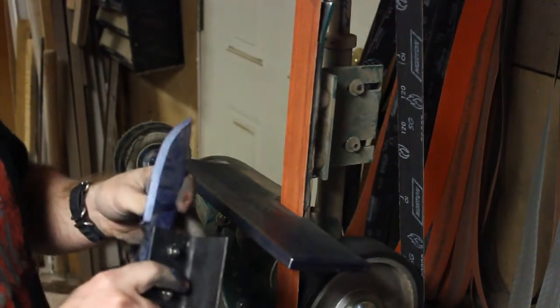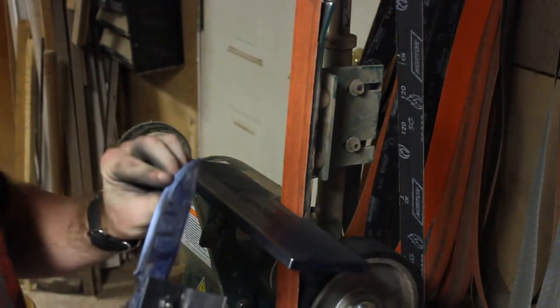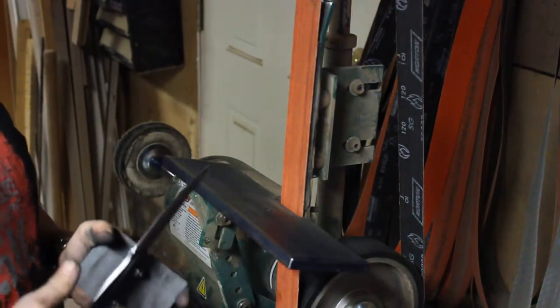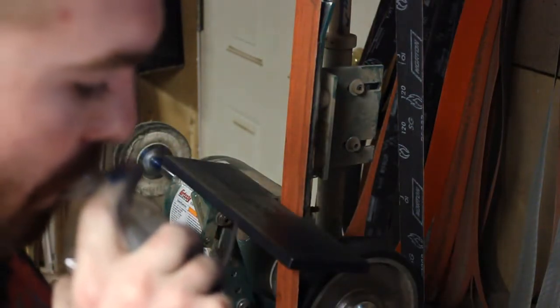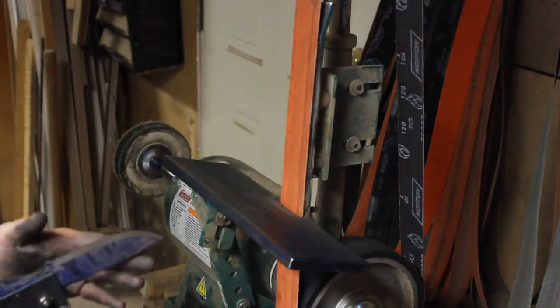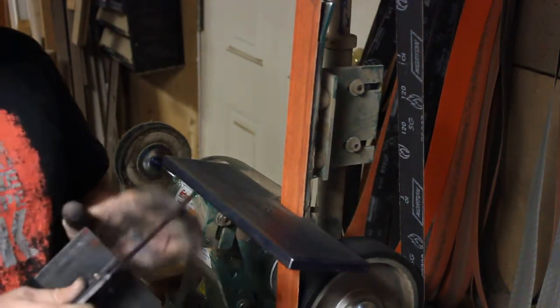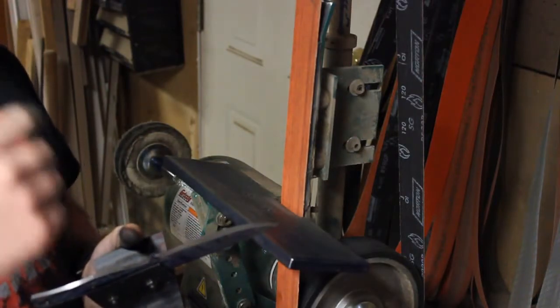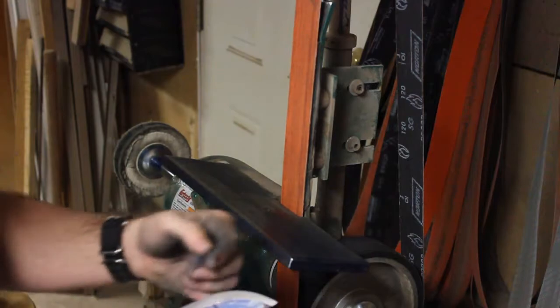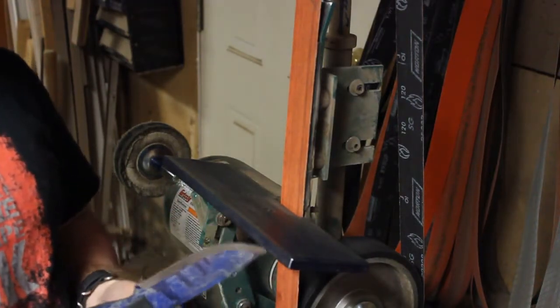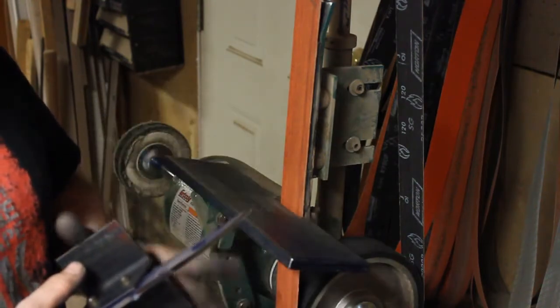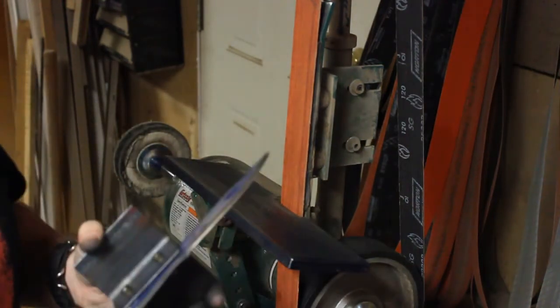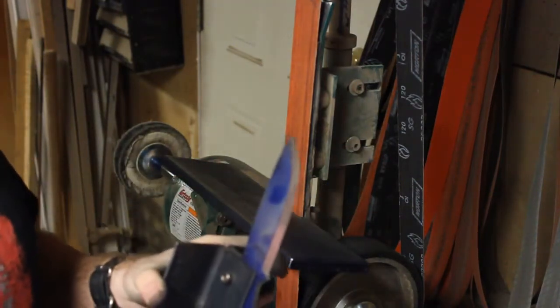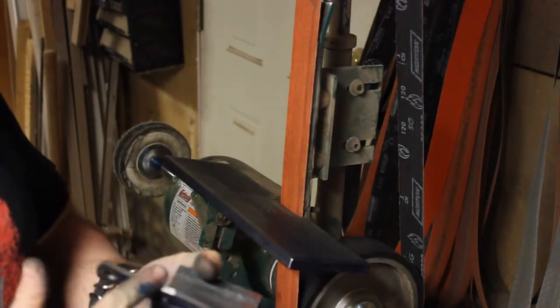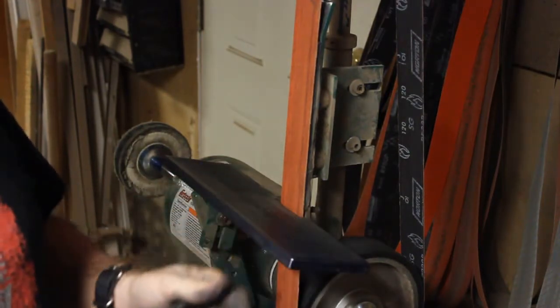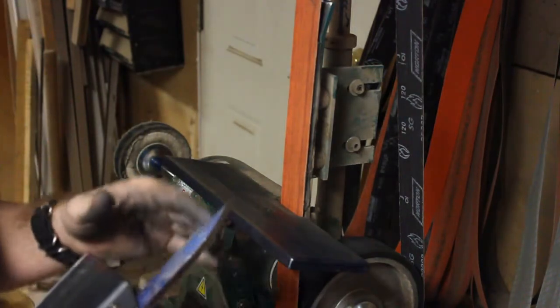Another thing, if you get your edge too fine before you go to do your heat treat, unless you want to start all over, you can take this belt and you can very gently knock off that edge that you've already got. Now, does that have problems of its own? Yes, you can dish out part of your edge, and that ruins your blank altogether. But this blank is slightly oversized, maybe by a 32nd of an inch on every line to begin with, because all of these lines are going to be ground again when the knife is almost finished. So take that into account.